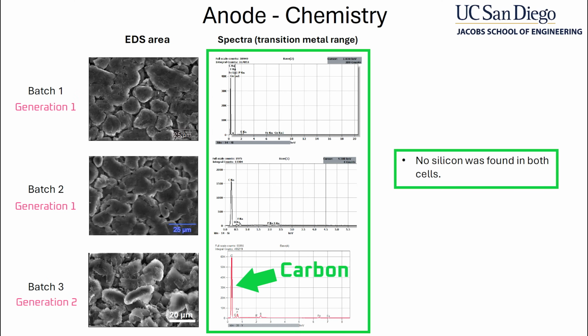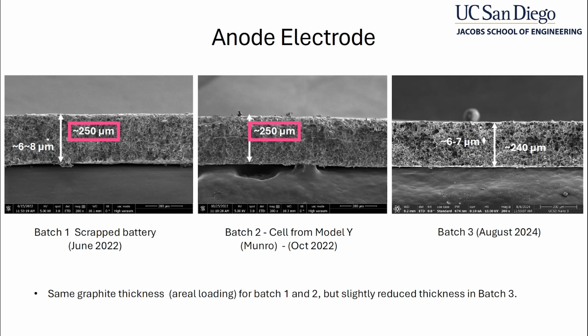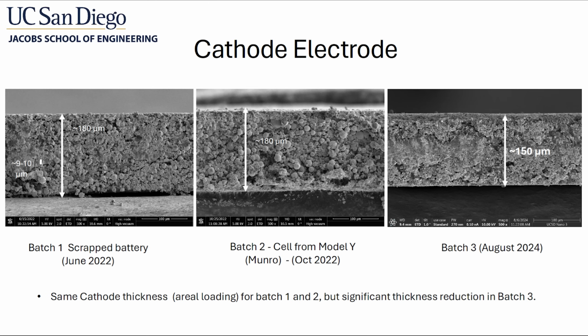That means if the Generation 2 4680 is using the same anode material as the Generation 1 4680, but the thickness of the anode has reduced from 250 microns to 240 microns, or about 4%, the cathode should also see a reduction in thickness of about 4%. But that's not what we see when we look at the cathode. Instead, the thickness of the cathode has gone from 180 microns to 150 microns, which is a reduction in thickness of 17%. That could have occurred in two ways.